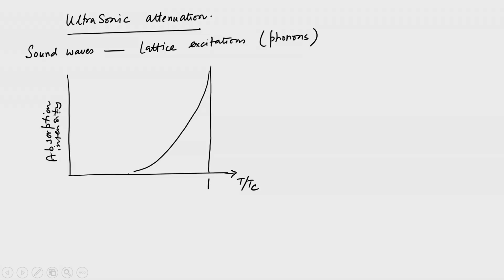Okay. So, one gets a plot like this. What it means is the following: below Tc, so this left side between 0 and 1, we have a superconductor, and this is the normal state. In a superconductor there are very few unpaired electrons, they are mostly Cooper pairs, which form the constituents of the superconducting state. And that is why the superconducting state has a gap.